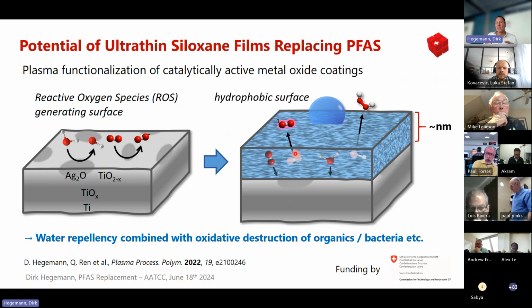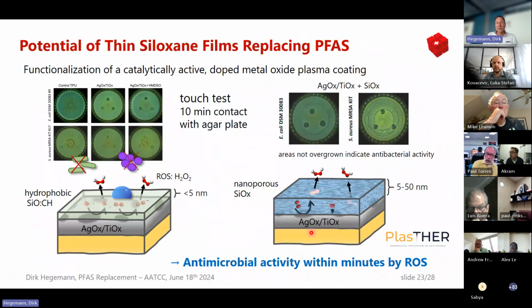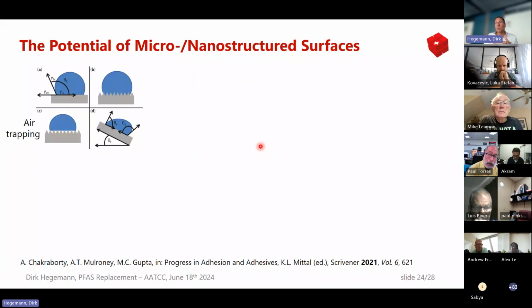And like this, we can combine repellency with oxidative destruction of organics, but also bacteria, which is currently our main interest. When you look at bacteria here with the 5 nanometer thick hydrophobic coating, we still see a good effect on some bacteria, a little bit reduced for some others for the hydrophobic. And we have more nanoporous coatings. That means better access of water to the catalytic active surface. We maintain very good oxidative destruction and antimicrobial effects. And that happens within minutes. It's not that this takes a long time. That would be one chance somehow to combine repellent effects with active surfaces.